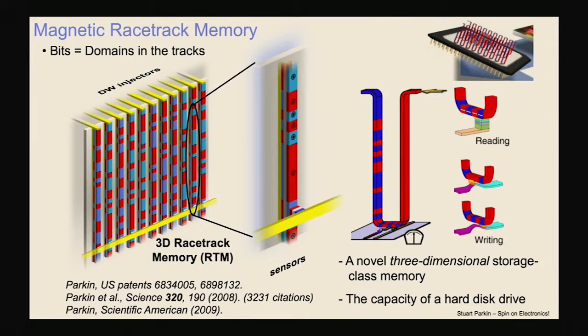And what's interesting is that over the last 12 years since I first proposed this concept, first we demonstrated it about 10 years ago, but in the last 5 years using spin orbitronics, we and others have demonstrated that we can move these domain walls with current pulses 10 times more efficiently than was even possible just 3 or 4 years ago. And this is why today racetrack memory is of interest to nearly all the major memory companies around the world. They're all interested in potentially working with us on taking the basic science that we believe is at the point where one could imagine building a technology based on this concept.